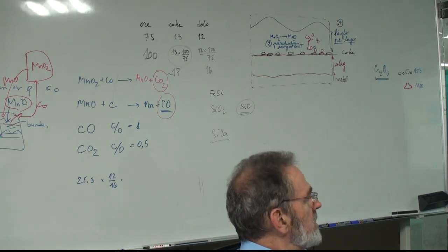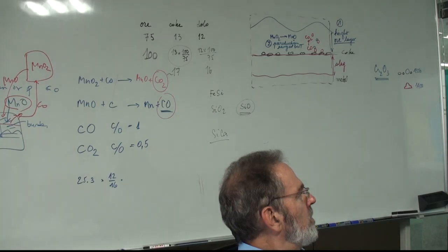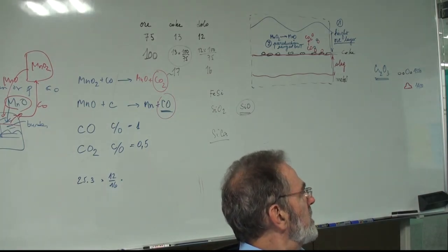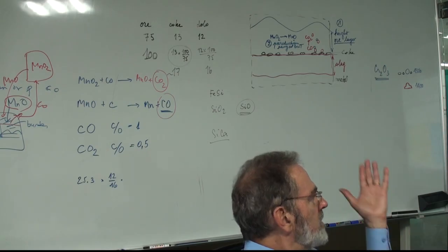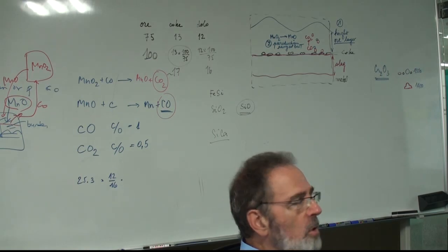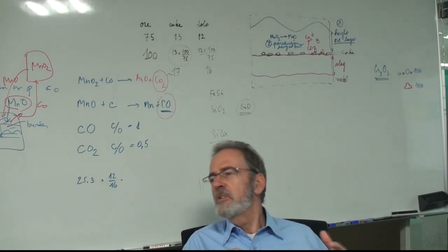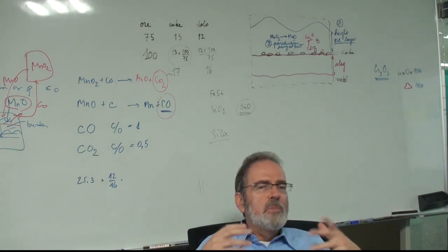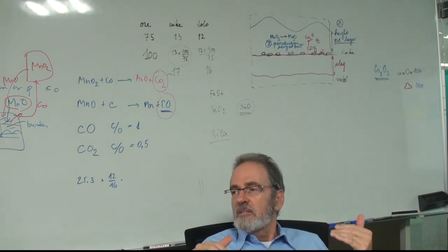Okay? And what we find out is 164 kilo, and of course we compare it with the input data, which for dry coke is 150, that's 149. So the calculation gives more. Why? I don't know. It's comparable, but it's more. And so there must be a reason why they announce less.